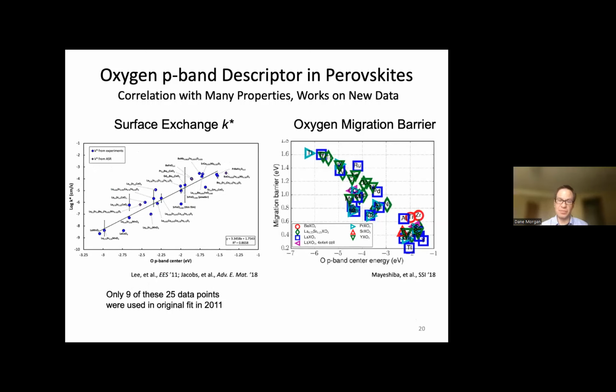And he looked across a bunch of perovskites. And he found that if you took the log of the surface exchange coefficient and you just plotted it as a function of the oxygen p-band center relative to the Fermi level, that descriptor I just described, then in fact, they fell pretty well on a line. And that meant we had a property that was very strongly correlated with the kinetics of oxygen in the material. Really, its ability to be an active oxygen material is really well captured by the surface exchange coefficient. And it correlated linearly with this very simple property we could calculate. So that showed a good strong correlation.